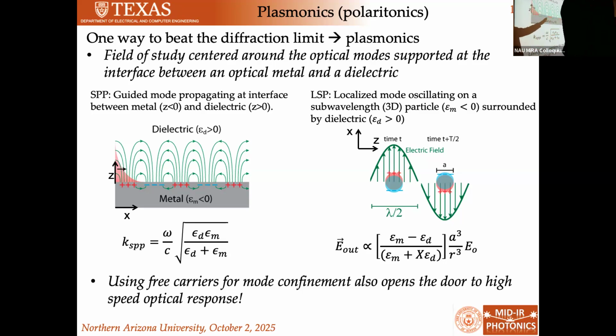We can also excite what's called a localized surface plasmon. This is a localized mode that is tied to some sort of 3D structure. In the simplest case, it might just be a sphere floating in vacuum. And again, you can see that in the denominator for the polarizability, or essentially the electric field tied to the outside of the sphere, we get very, very strong electric field enhancement when the permittivity of your metal is equal and opposite-ish to that of your dielectric. This X is just some scaling factor depending on the geometry of your structure.